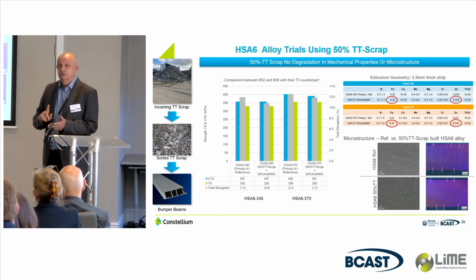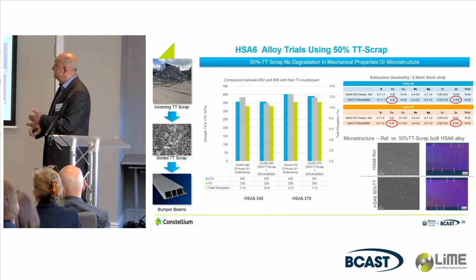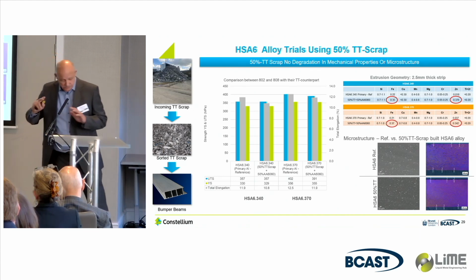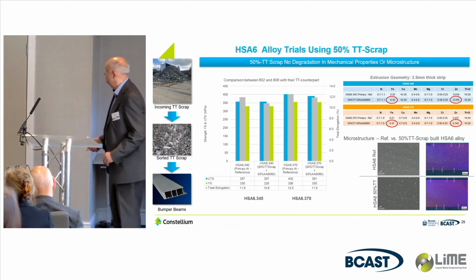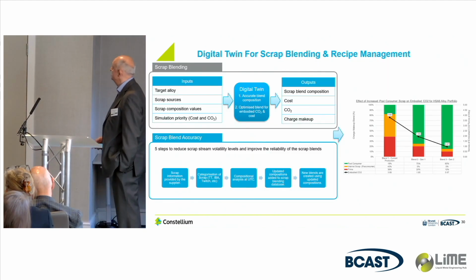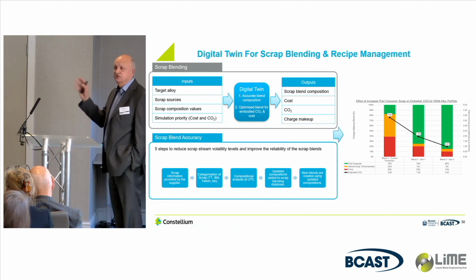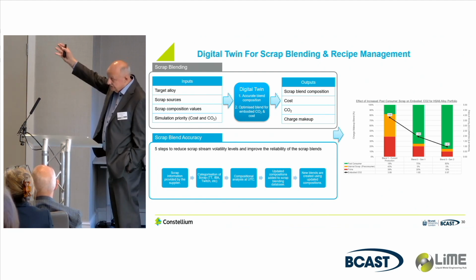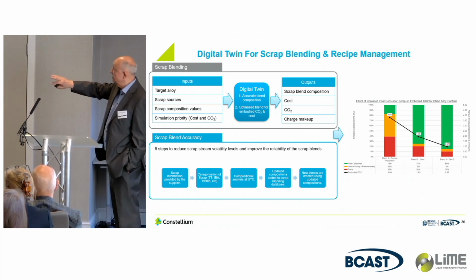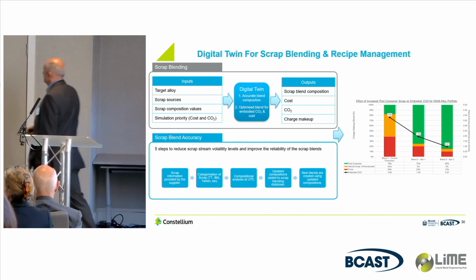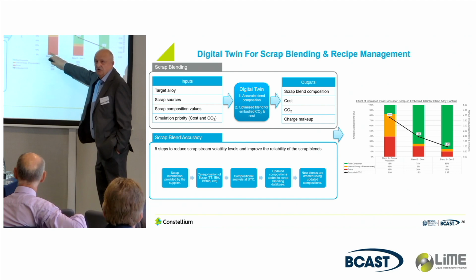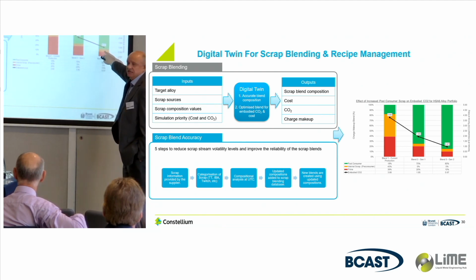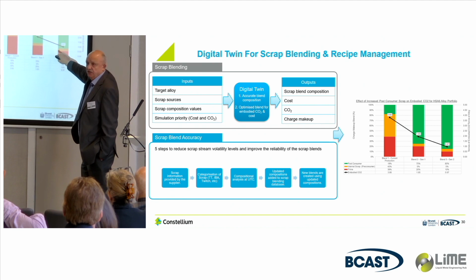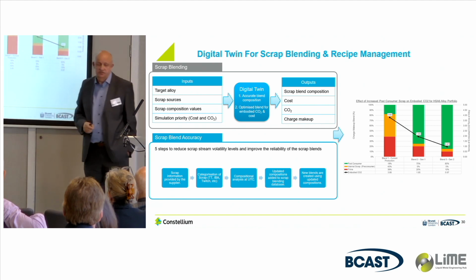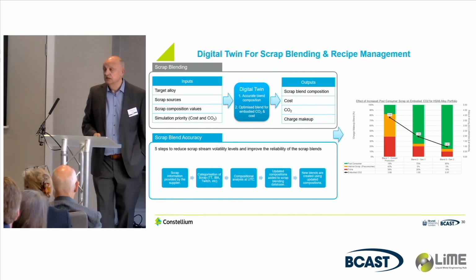And that includes the pre-treatment. And the embodied CO2 in this material, we're now able to also model. We have hundreds and hundreds of compositions from our partners, and we've actually produced, in this case, a digital twin where we can show, obviously depends on the prime. This is a relatively good level, low level of prime. But we can take this down to less than 1 tonne of CO2 per tonne of aluminium with different mixtures of the various grades of scrap.